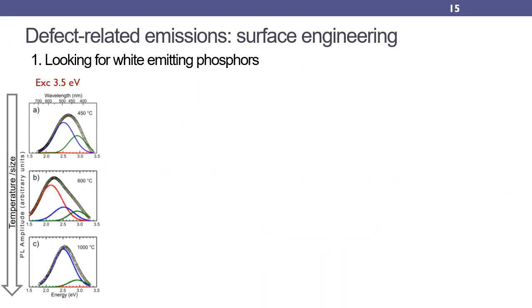All the explained results display the possibility to control the emission properties of hafnium oxide nanocrystals by simply selecting the thermal treatment that influences the surface defect arrangement. In particular, hafnia intrinsic defects can be efficiently excited by near UV light, but the color of the final output varies according to the surface-to-volume ratio, the size, the porosity, and the crystalline degree of the nanocrystal. While annealing the hafnia nanocrystals, we witness a change of the spectral features.